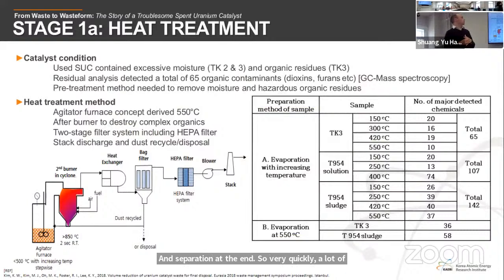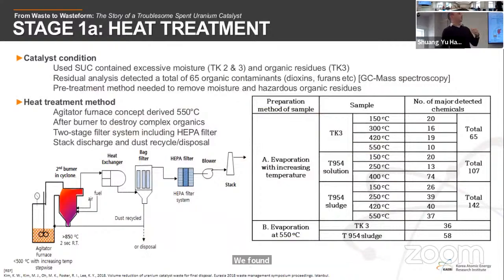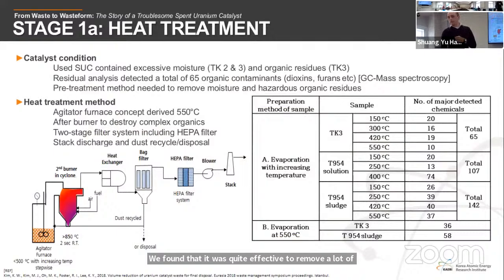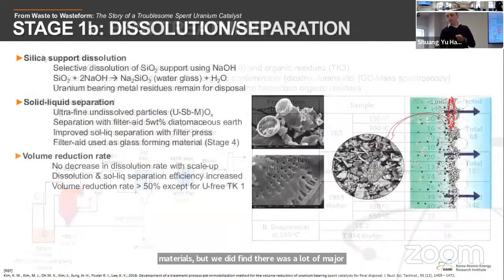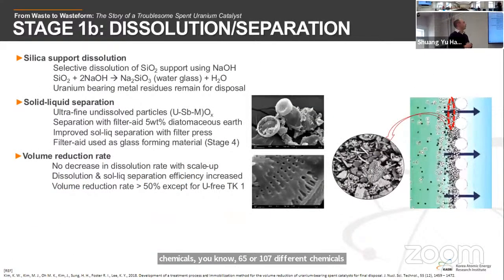I'll get onto some more of the detail later. But essentially, we had a heat treatment process in the beginning. This was an off-gas burner to burn off any of the organic material that was within the catalyst. We found that it was quite effective to remove a lot of materials, but we did find there were a lot of major chemicals, 65 or 107 different chemicals, depending on the actual waste itself, which is not very good.